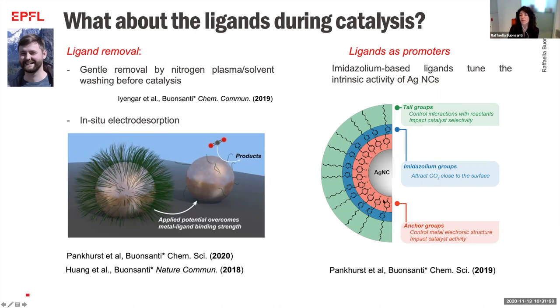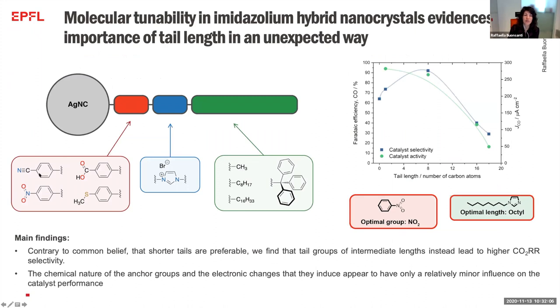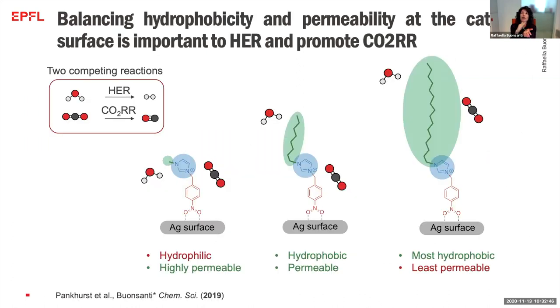And his first work was about using these imidazolium-based ligands, where basically the imidazolium group interacts with the CO2. And then he changed the anchor group and the tail group. So he really did a very systematic study, keeping the imidazolium group and changing the tail length of these ligands. And we found again something that was quite surprising, thanks to this tunability that we are able to achieve. So actually we found that the highest efficiency towards CO and the highest intrinsic activity, which is represented by the current density normalized by the surface area, is that the middle tail length is the best for achieving selectivity and activity.